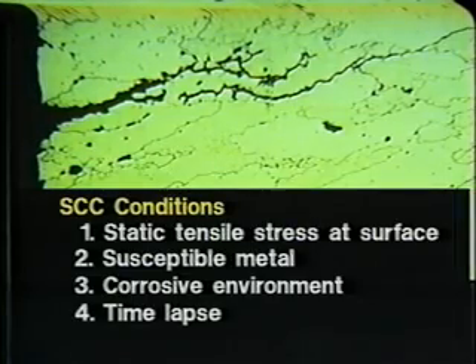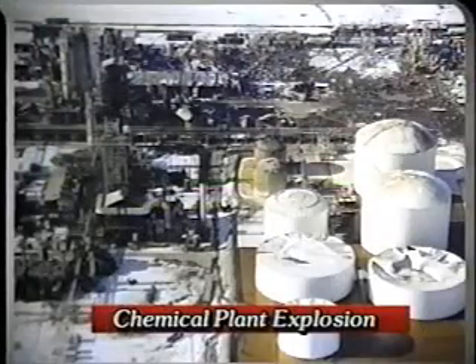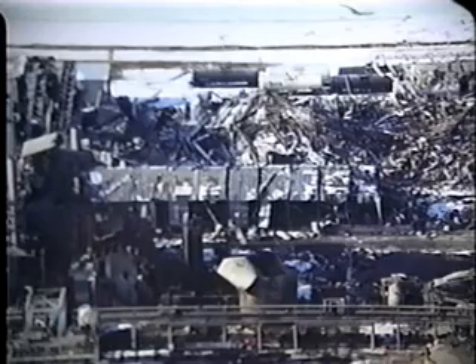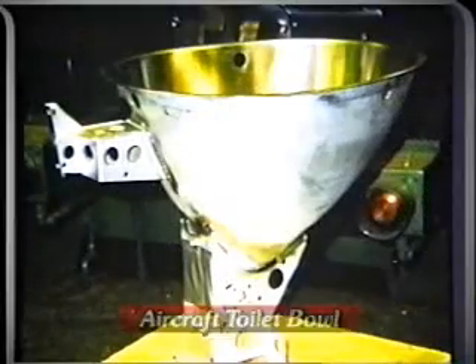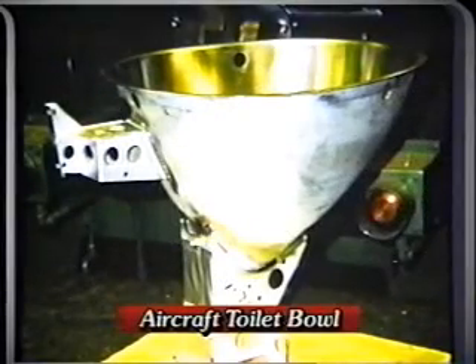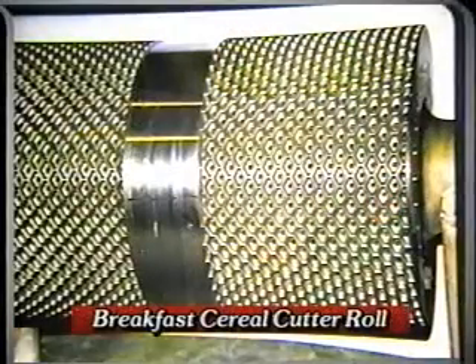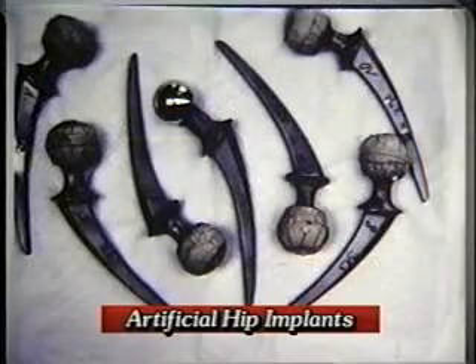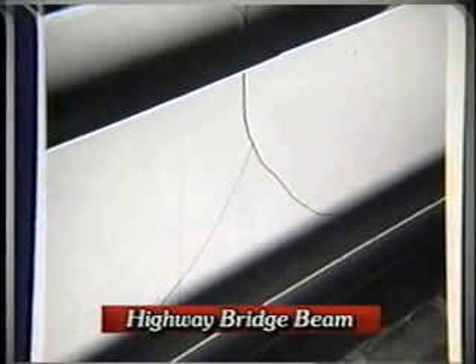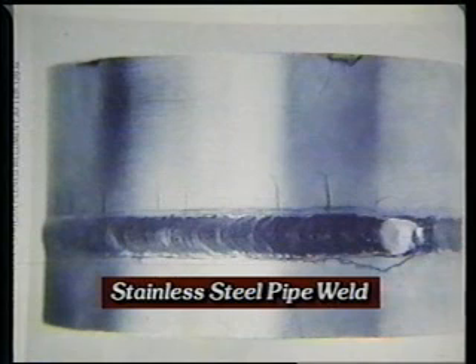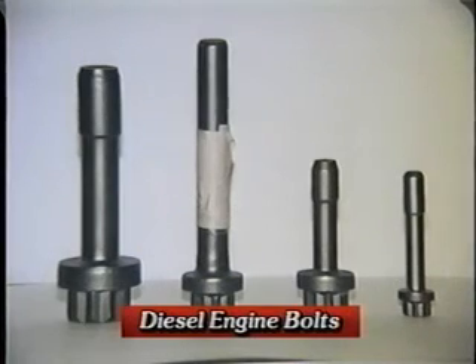Structural failure due to SCC is often sudden and unpredictable, occurring after as little as a few hours of exposure, or after months or even years of satisfactory service. Virtually all alloys are susceptible to SCC by a specific corrodant under a specific set of conditions. Often, the corrodant will be considered very mild in terms of general corrosion, but will cause severe cracking where tensile stresses are present, such as in the heat-affected zone of a weld or in a highly stressed fastener.